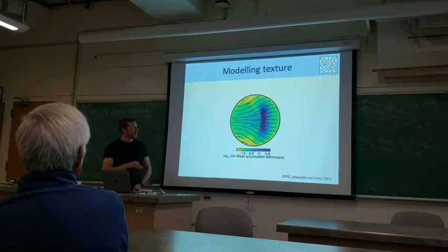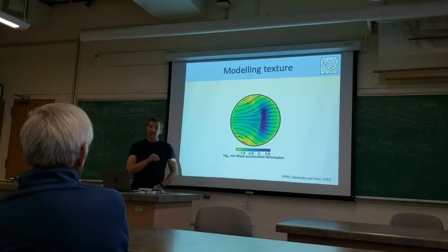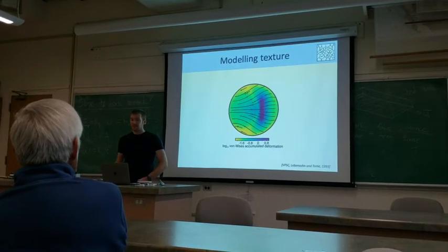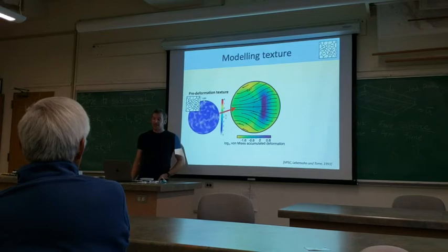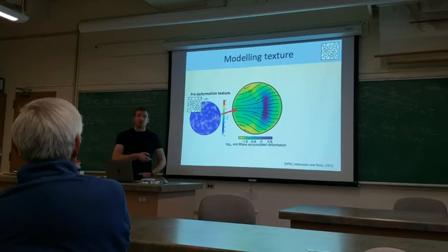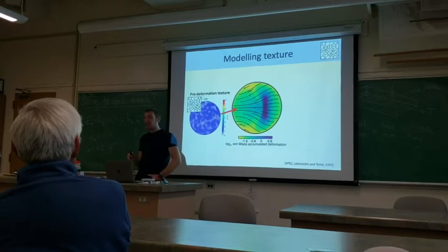We then modeled the deformation of a set of crystals along each tracer on these given slip planes in the presence of this strain field, using the viscoplastic self-consistent code, or VPSC. We calculate how a polycrystal would generate texture given a strain field and the properties of a single crystal. We start with a polycrystal comprising 1,000 randomly oriented single crystals, and we expose it to the strain caused by this growth model.